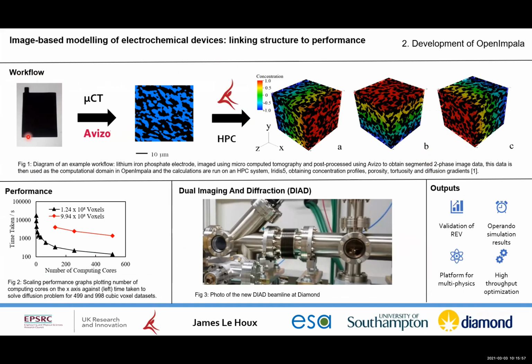So if we look at a typical workflow of what I was up to, I was making a lithium iron phosphate electrode here for a pouch cell, sticking it in a CT scanner, obtaining a 3D data set, and post-processing that into a two-phase segmented data set. We can see here the blue relates to the solid structure, the black is that porous phase where the electrolyte percolates through. And then we can use that as the computational domain to solve transport problems. So we can see here we've got a steady state diffusive flow in the X, Y, and Z directions. And we can start to use these techniques to inform our design.